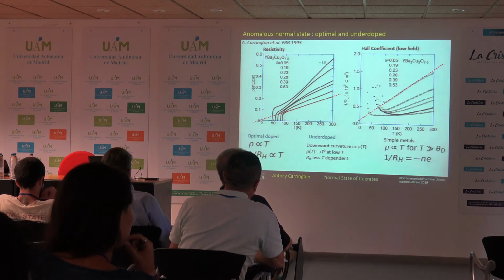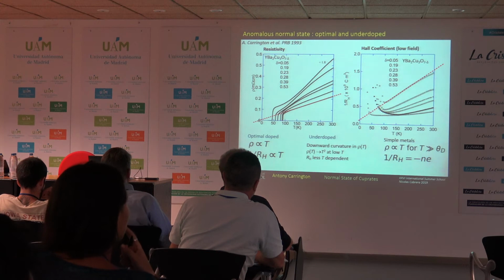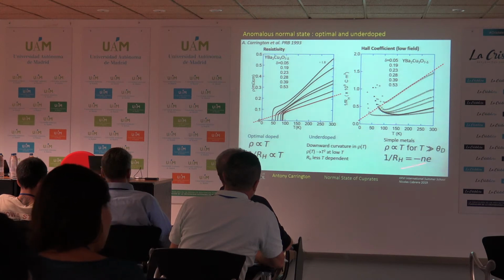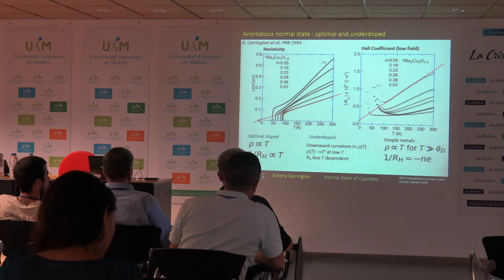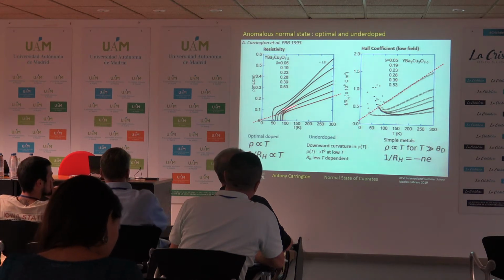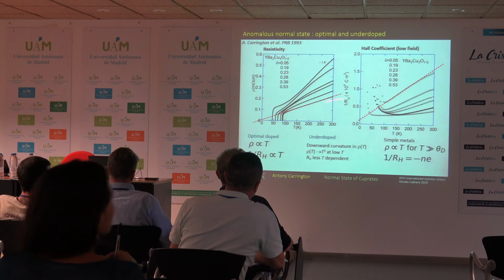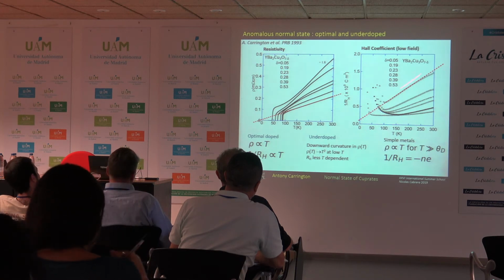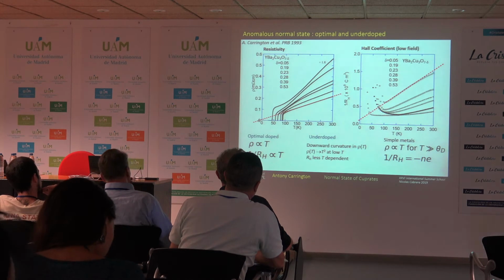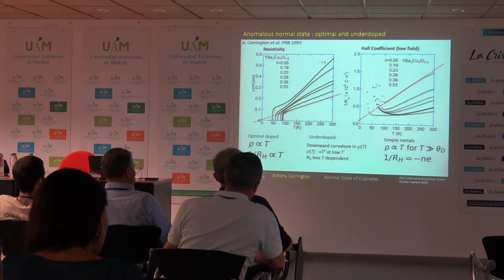And so you might immediately think, okay, that must mean that the carrier density is changing, right? But like a semiconductor. But we know from other measurements, optical measurements, but also just from looking at the resistivity, that that's not the case. If you were immediately losing carriers, you wouldn't expect the system to be metallic. Okay, so you've got these two anomalous properties.